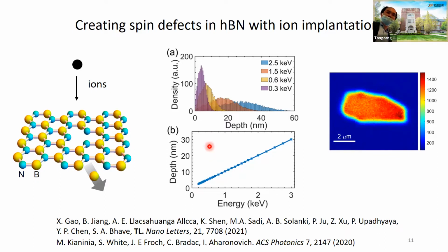Okay. So in this case, it's not like a focused ion beam. Right, you don't focus the ion beam. Our own ion implanter can irradiate the flake with a size up to about 1 centimeter. So it's pretty homogeneous.